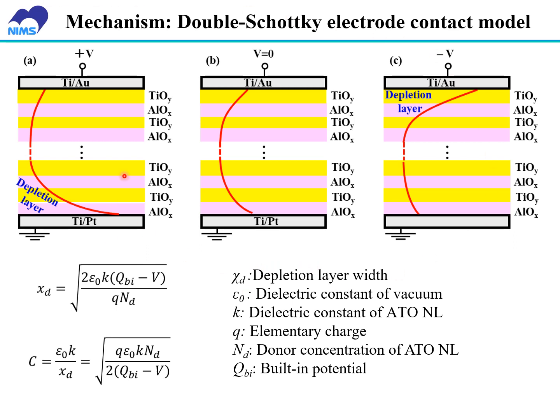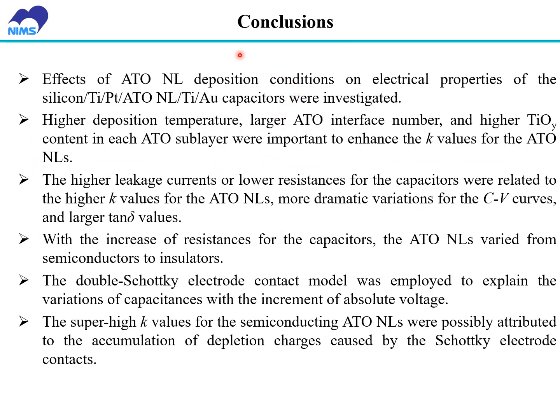Therefore, we believe that the super high dielectric constant of the ATO nanolaminate is attributed to the double Schottky electrode contact model. In conclusion, in this study, the effects of ATO nanolaminate deposition conditions on the electrical properties of the capacitors were investigated. The higher deposition temperature, larger ATO interface number, and higher titanium oxide content in each ATO sublayer were important to enhance the K value for the ATO nanolaminates. The higher leakage current or lower resistance of the capacitors was related to the higher K values for the ATO nanolaminates.